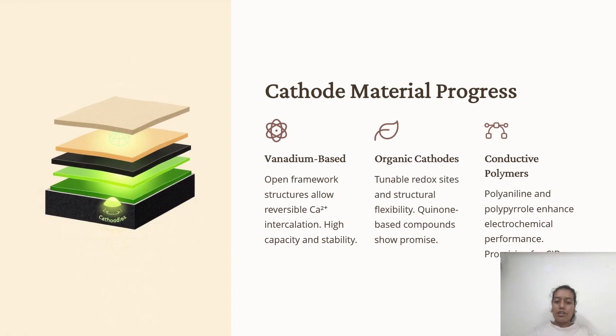Their open framework structures allow for reversible calcium intercalation. For example, hydrated vanadium oxides can maintain over 90% of their capacity even after thousands of cycles. This is because their structure helps in accommodating the larger calcium ions efficiently.